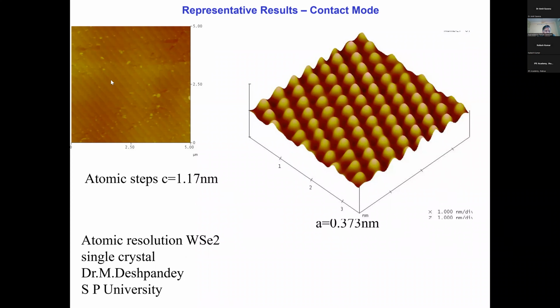So you can see these are all very beautiful, good quality crystals grown by means of screw dislocation with the Burgers vector of 1.17 nanometer, 11.7 angstrom, which is nothing but the c-axis. It can be c initially, then 2c, 3c, integral multiples of that will happen. It's the beauty of crystallography.